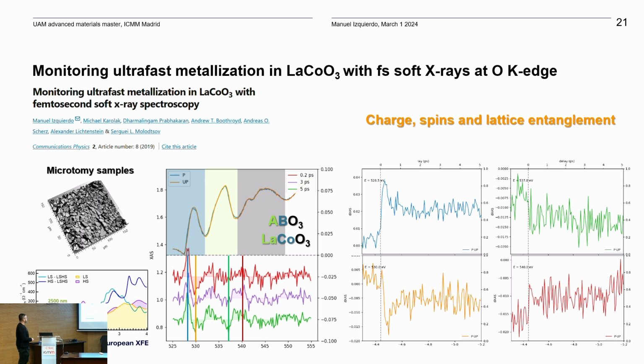The problem with this material is that it has a rhombohedral structure, and if you grow it as a thin film, this will be changed into orthorhombic, and as a consequence, all the magnetic properties of the system are changed. So there is only one way to address this system, and this is by studying single crystals.